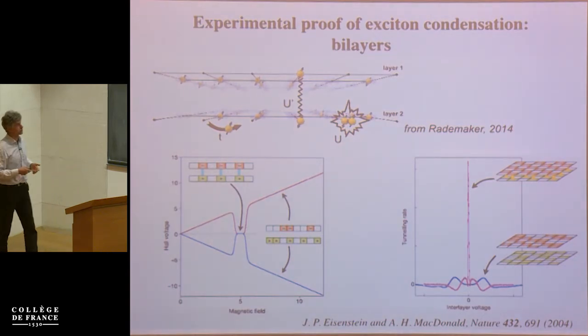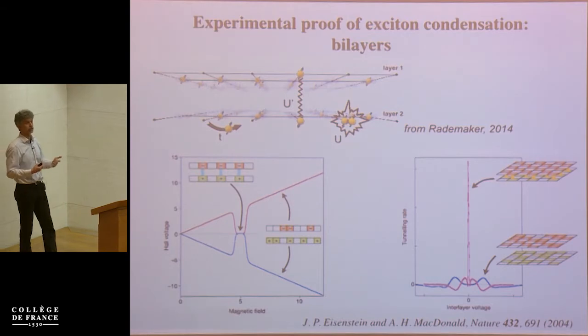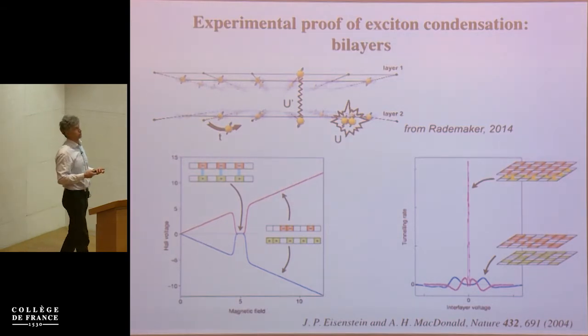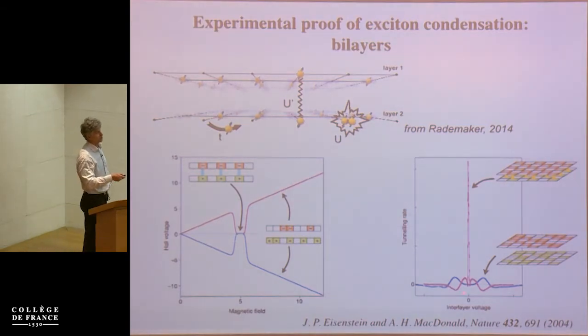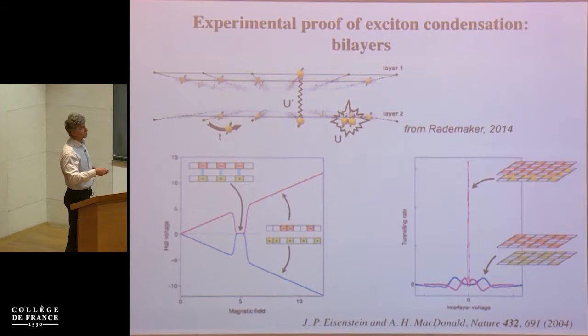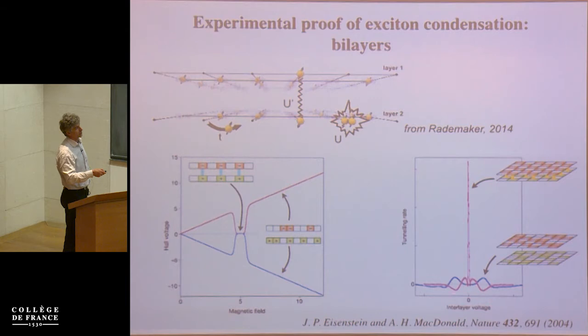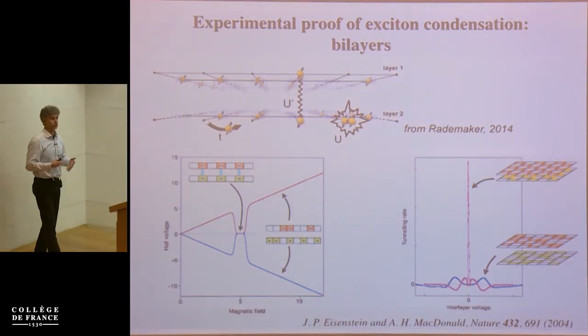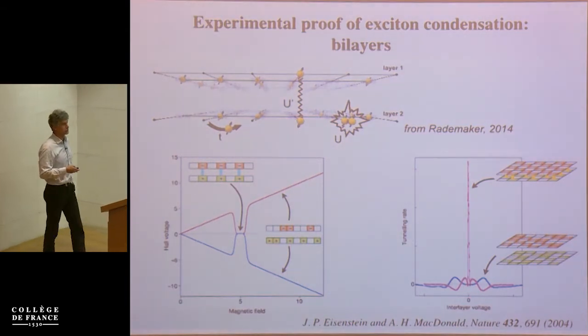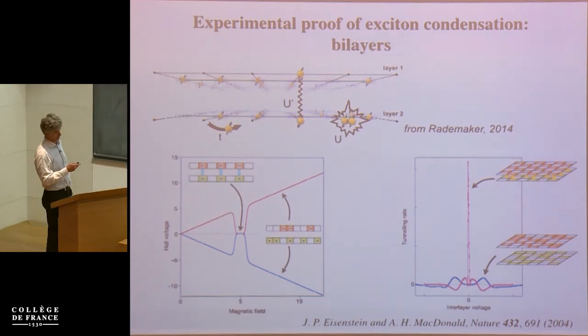Of course, this is not a proof that we have a coherent condensate. To prove that they have a coherent condensate, they measured the tunneling rate between these layers. This is the tunneling rate in the normal state when there is no condensate. And then when they got to this excitonic condensate regime, they saw a huge peak at zero bias voltage, which was the proof that there is indeed a coherent condensate of excitons.